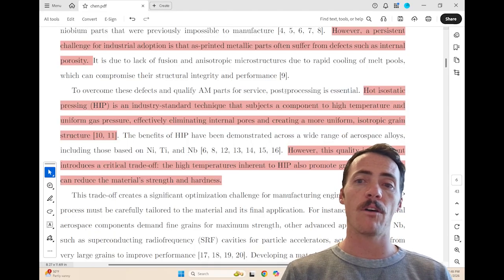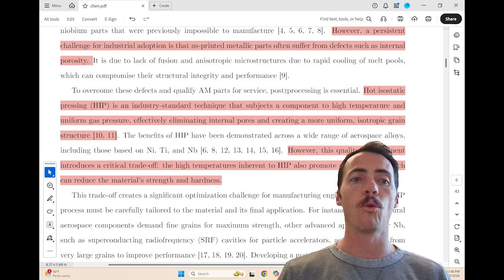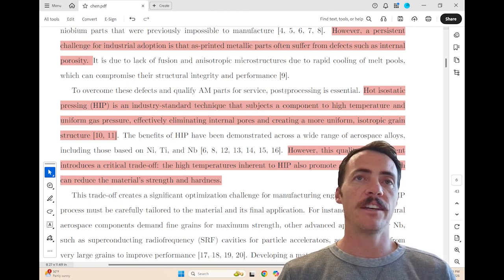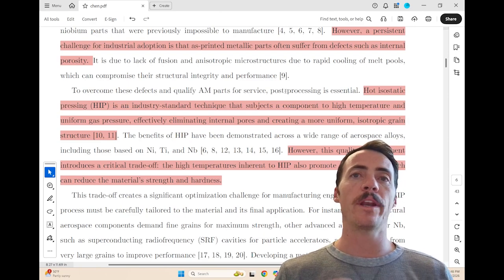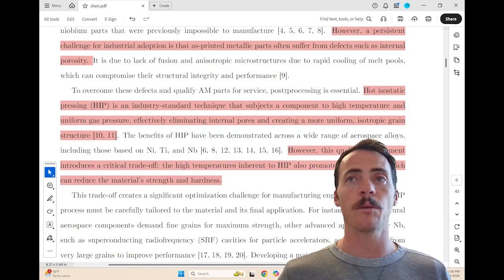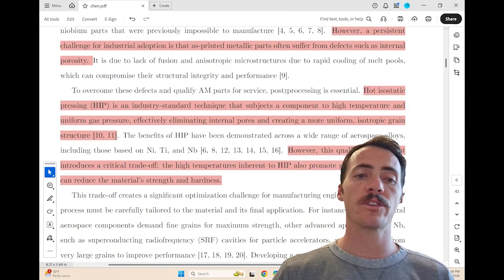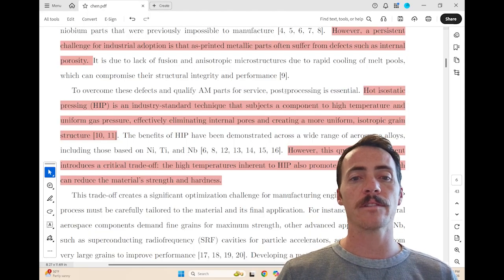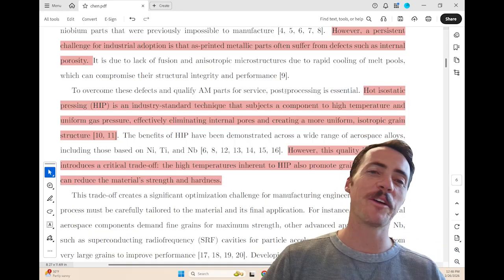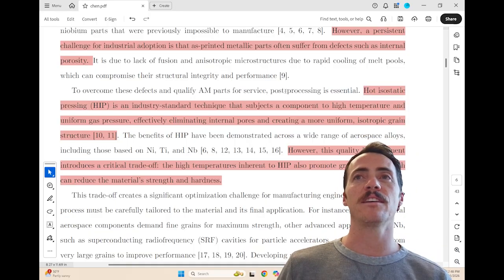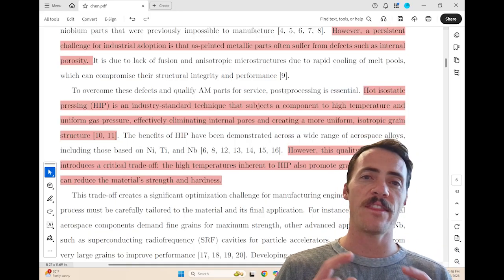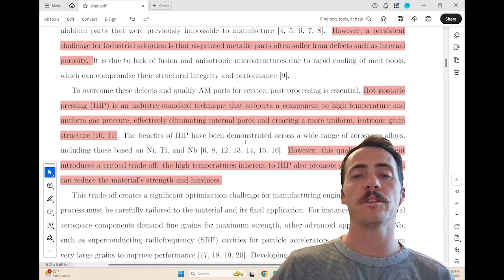The grains themselves become more isotropic, more uniform, but in that process, they typically grow. And as grains grow, we know that traditionally comes with the trade-off in terms of a reduction of material strength and hardness. In a perfect world, we would both get rid of the porosity while minimizing the reduction in strength and hardness. And that's what these authors are going to try and demonstrate here.